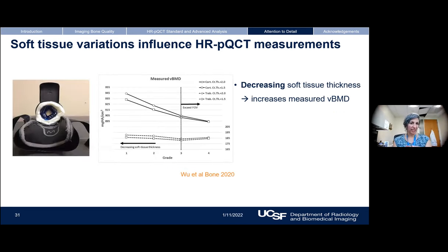So we were simultaneously performing a very similar study, but our question was flipped. We wanted to calculate the impact of these soft tissue artifacts in the scenario of major weight loss following bariatric surgery. So what we used was a phantom that represented both a homogeneous trabecular compartment and a cortical compartment wrapped in gel meant to mimic muscle tissue, and then wrapped in fat. And that's what you see on the left there. And what we found was, with decreasing soft tissue thickness, now we're talking about the scenario of weight loss over time, decreasing soft tissue thickness increases our measured vBMD, and it was much more dramatic in the cortical versus the trabecular compartment.